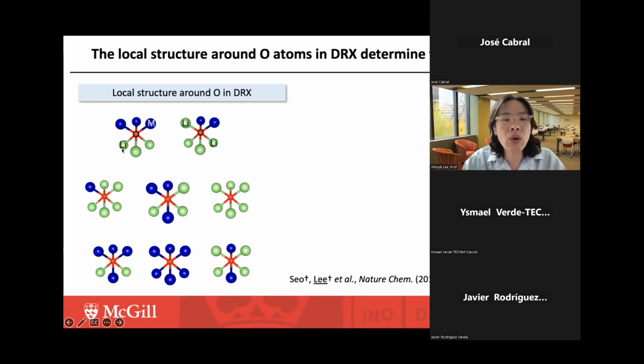And there can be a local structure on oxygen where there are 3 transition metals in the transition metal layer, that's here in the layer side, and then you can find other lithium ions nearby. But now in the disordered rocksalt structure, we can imagine that the occupancy of these sites is nearly random. So we can imagine that there are many different types of local structure around oxygen.